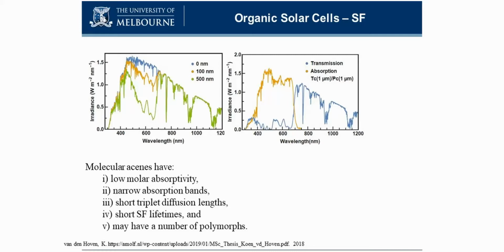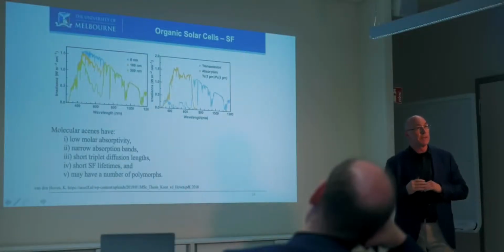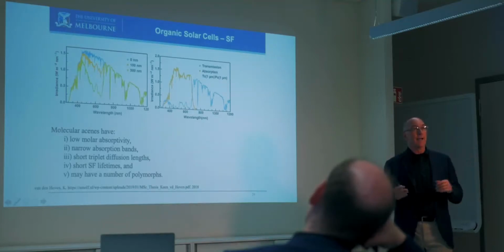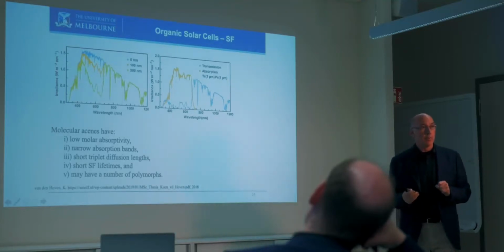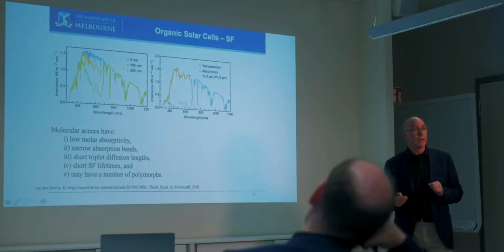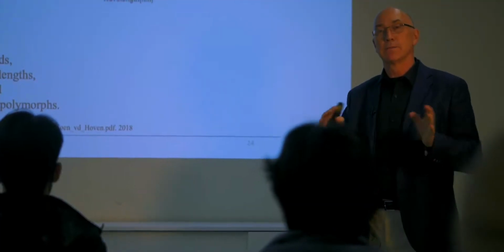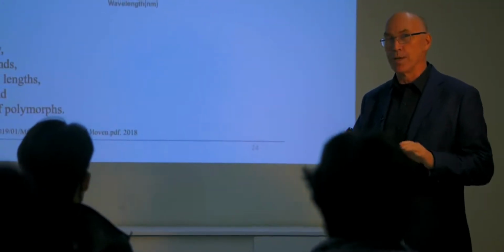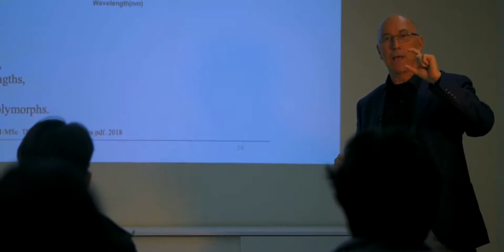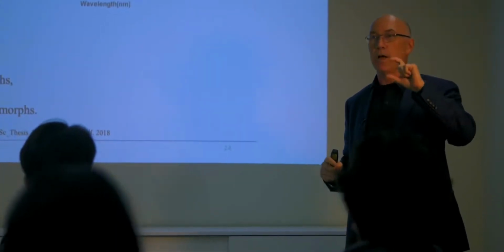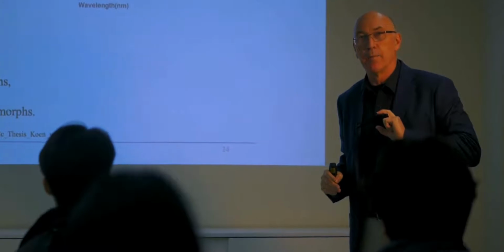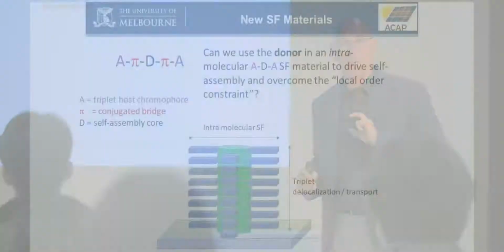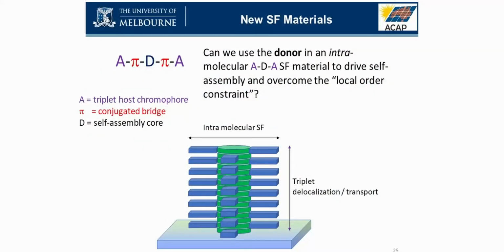And so if you look at most of the devices in the literature where they say they do singlet fission and they have really good external quantum efficiencies, i.e. they're getting more than one electron per photon, these are, I don't want to say manipulated, but basically they are calculated by having a very thin film and saying of the light absorbed, we are getting 120% efficient collection. But they're not absorbing all the light available. And so we have a long way to go. So we wanted to change that.